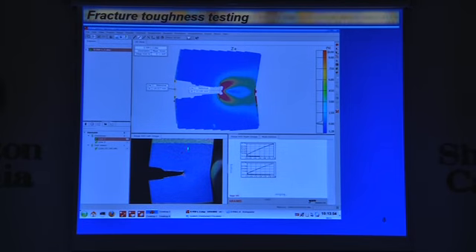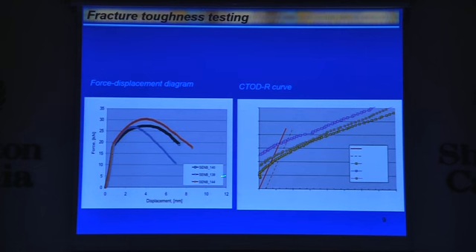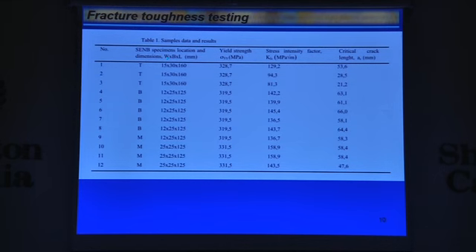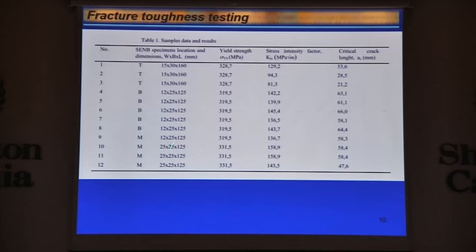So you can see that it is actually still a ductile material, and for each place we have 3 specimens. When we tested, we got these load-displacement curves and these resistance curves. I apologize, these remarks disappeared from this kind of presentation. Sorry. You can see that we actually tested different geometries and dimensions of specimens.